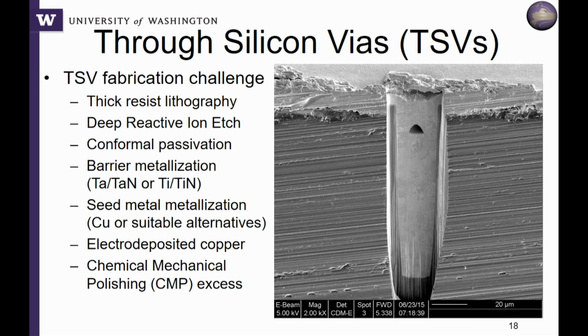The challenges are that you have to do really thick lithography, so you're limited on what you can resolve. You have to do a process called deep reactive ion etching, where you're actually boring a hole down into the silicon itself. In fact, when I was talking to Jimmy before, they were using a laser to do some surface analysis. We were trying to do laser drilling, and that had huge amounts of slag. So we had to develop new etch techniques to get a hole through a chip without a big plume or something we had to clean up on the surface.